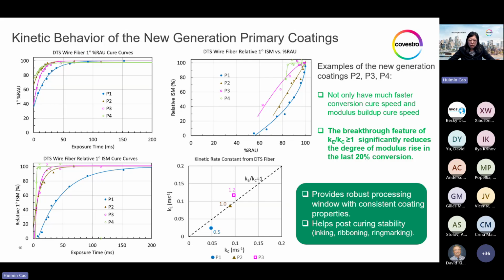It provides a robust processing window with very consistent coating properties. And it also helps post-curing stability. And this is very important, as during the cable process, such as inking, ribboning, ring marking, the coated fiber will go through additional UV cure.